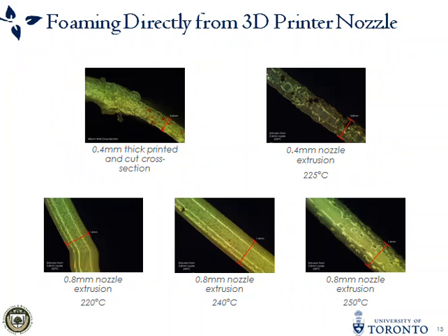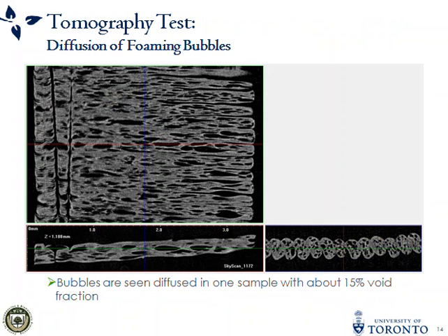So what we get when we extrude a string of this material out of the 3D printer nozzle, you can see in these examples the chemical blowing agent is releasing foam and is diffusing at different rates throughout the strand, and we can characterize this through studying it. Here's a tomography test I did with a sample of not just the strings but printed in a simple object. So you can see bubbles in all three orthographic projections, and for the first time we're introducing a foam from a 3D printer in an actual object.